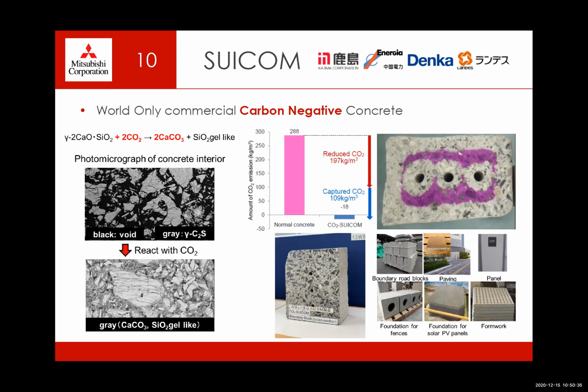We will then put that mixture into a curing chamber and capture CO2 into the concrete itself. The graph in the middle shows the total reduction volume. The 197 kilograms per cubic meter is the reduced volume by replacing the cement with the additive, whereas the 109 kilograms is the CO2 captured during the curing process in the chamber. By combining that, this will exceed the total emission from a normal cubic meter of concrete, which is why we call it a carbon negative concrete.